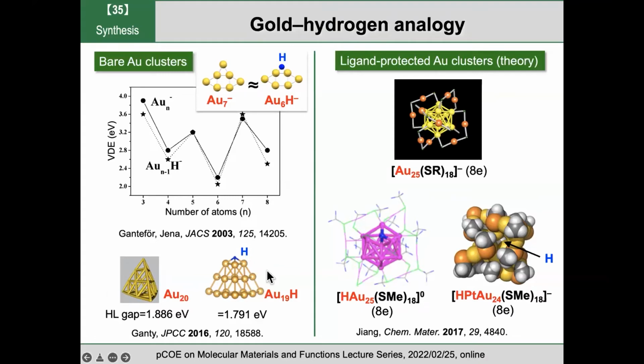But in order to stimulate reactions, we have to activate the clusters. So I'll show you our approach. We use hydrogen as an activator, and according to the gas phase studies, hydrogen mimics gold. Okay, so the electronic structures of Au7 and Au6H are very similar. Electron affinity is very similar, and one of the gold atoms of Au20 can be replaced with hydrogen, and the HOMO-LUMO gap is almost equivalent. So hydrogen mimics gold in the naked gold clusters.